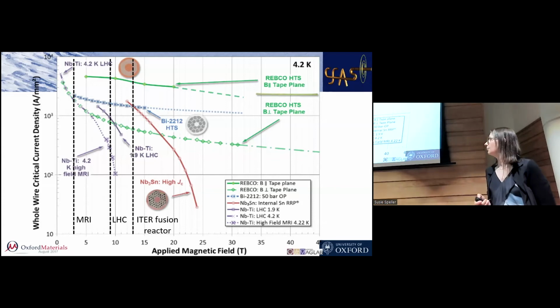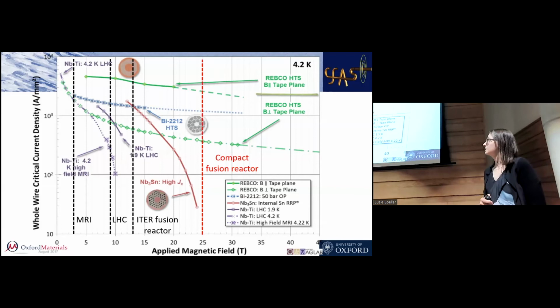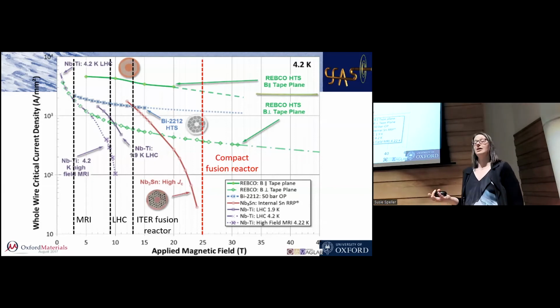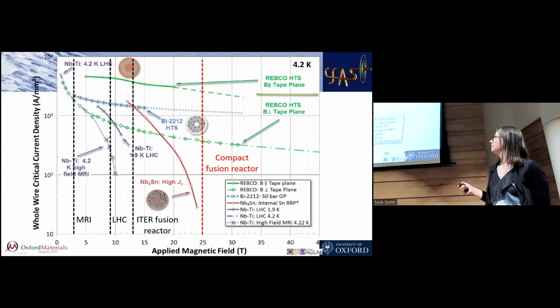But if we look at these compact tokamaks that are being designed now, they need 20, 25 Tesla. We're talking about high temperature superconductors. So the blue and the green lines here are the high temperature superconductors. They're not only good at working at high temperature, they're also good at working at very high magnetic fields when we cool them down. So there's a couple of choices, but the one that's probably going to be used is this REBCO, it's called, or YBCO.